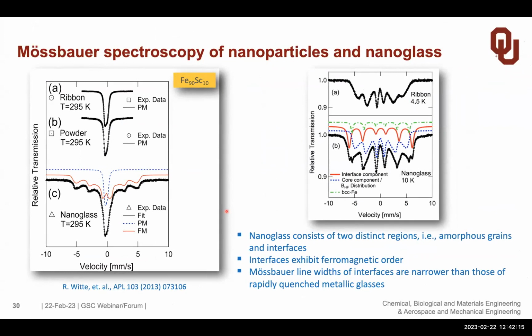And yes, indeed, the structure is different. And I would like to show you this. And this is what we have done using Mössbauer spectroscopy, which is a technique you might not even have heard about, but that's okay for the present. It looks at the environment of iron 57, which is a naturally occurring isotope of iron. So it gives you information of the environment, both in structure and also in magnetic structure of an iron atom in your material. And in this case, this is iron scandium material, which we have performed as rapidly quenched by rapid quenching, or the powder, which I use to consolidate later.